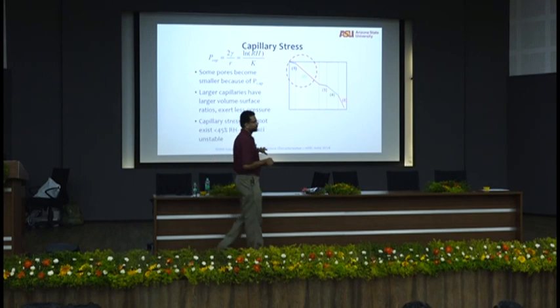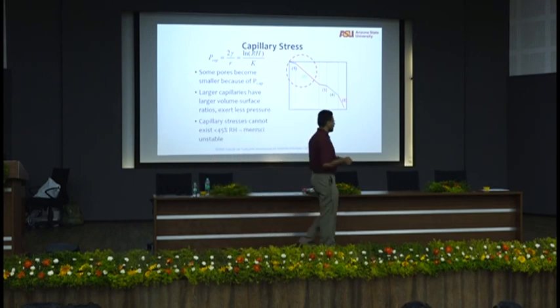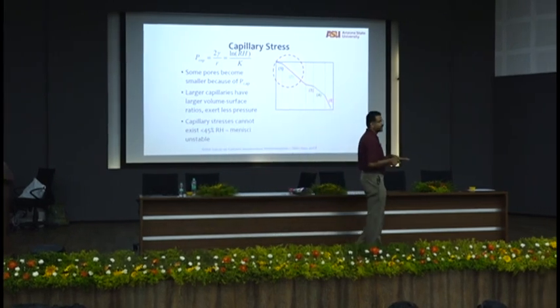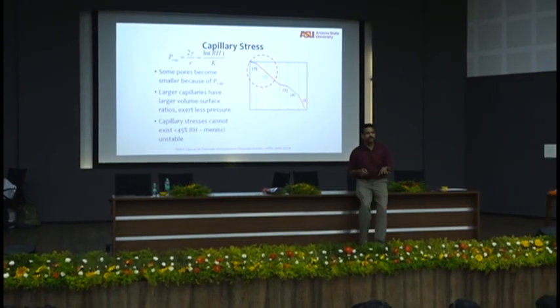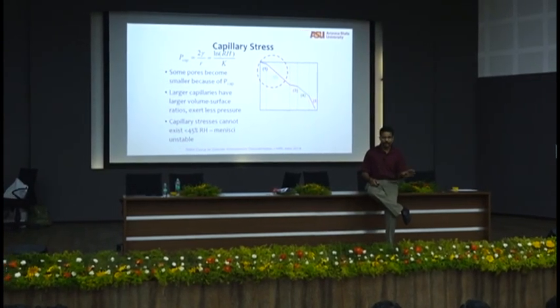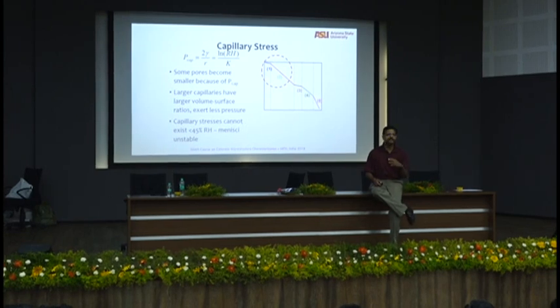This shrinkage is popular in most parts of India where there is reasonable amount of rain. Forget Rajasthan, forget very dry areas, because you will never drop really lower than 45% RH, because you have seasonal rains replenishing water in your concrete all the time. So this mechanism, if you have drying shrinkage, it is this capillary stress mechanism that happens.